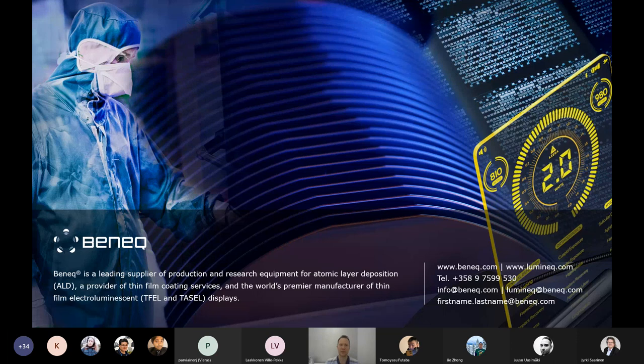And some surfaces that are difficult to coat may take a few ALD cycles where there is practically no growth. But once it starts, there may be a kind of island-type growth on certain areas, and when the islands grow together, after that you will have a completely normal ALD deposition. So in practice, you might lose your first 1 or 2 nanometers for this initiation, but after that it grows normally. If you're trying to deposit a 1 nanometer film, it may be difficult. But if you're depositing a 100 nanometer film, then that's probably perfectly all right.